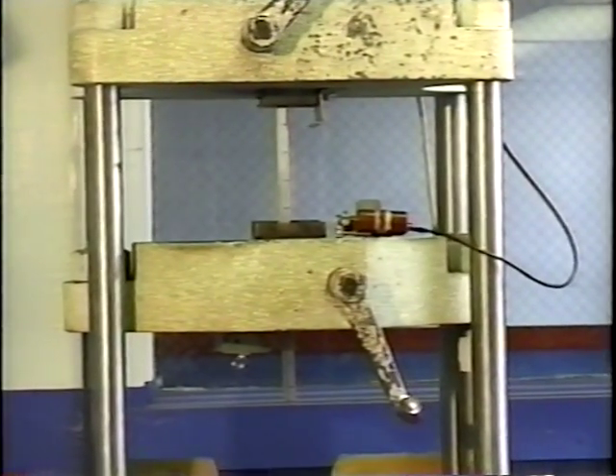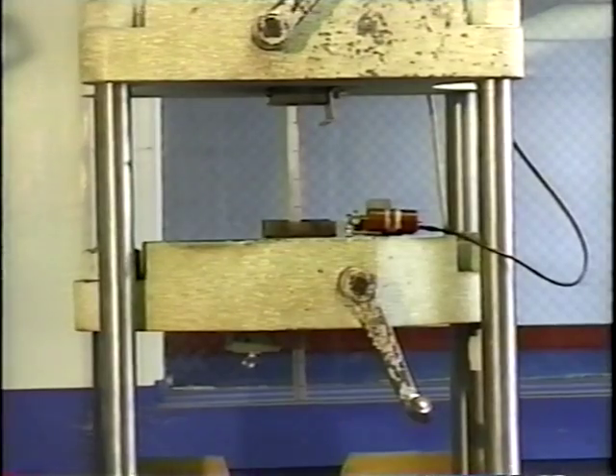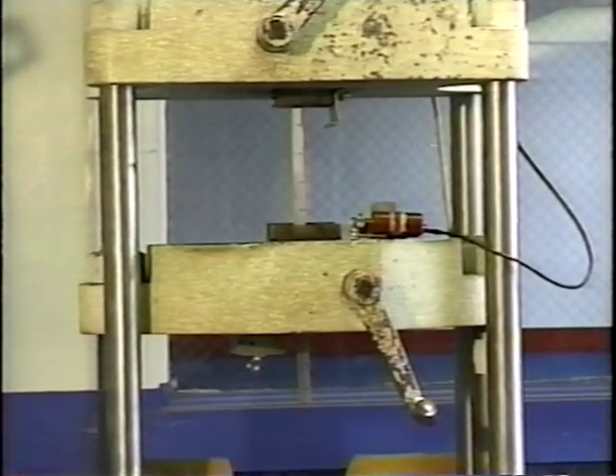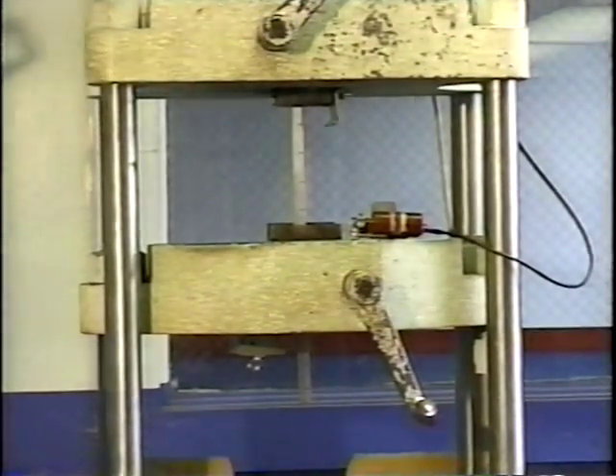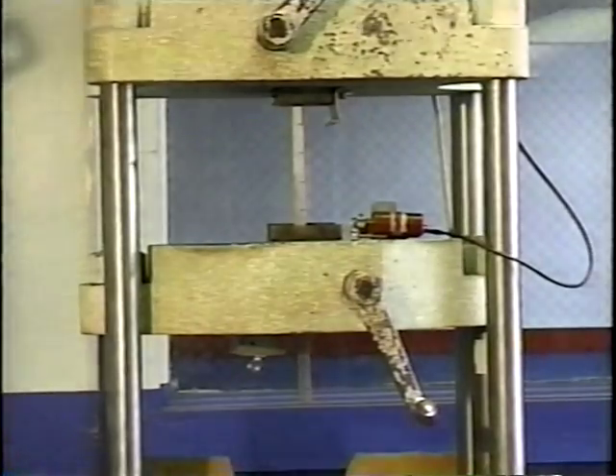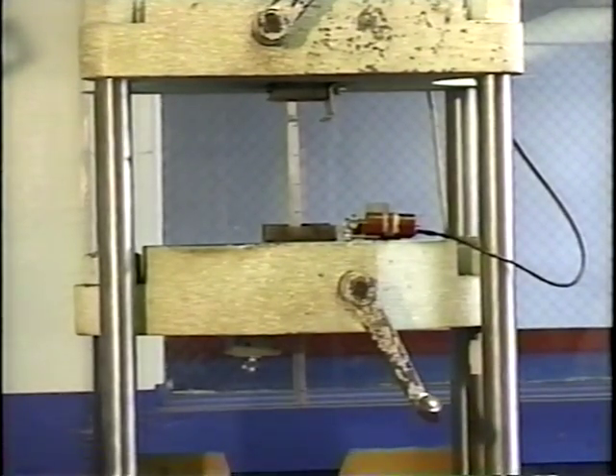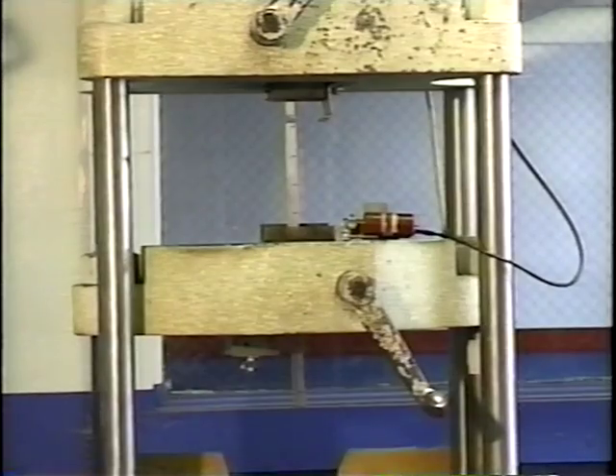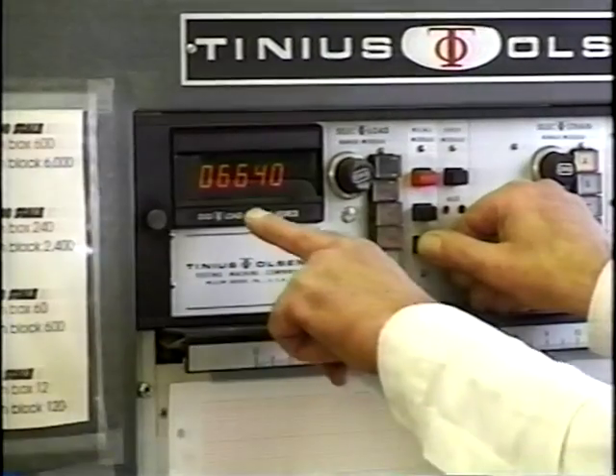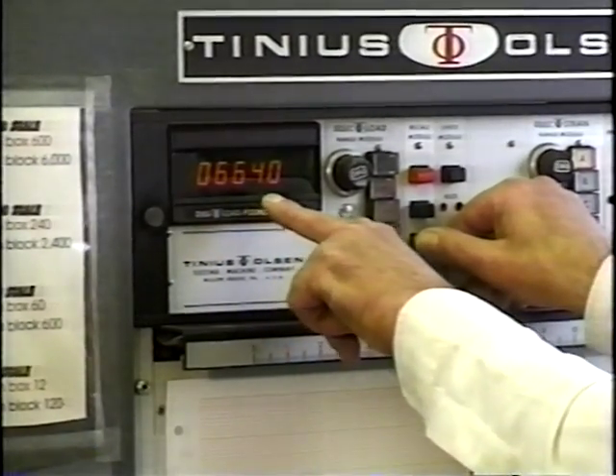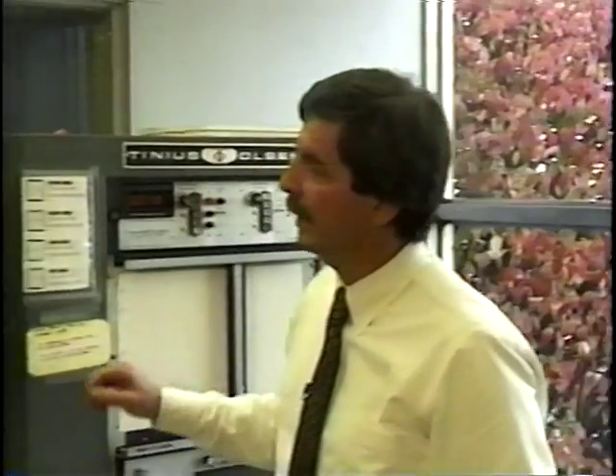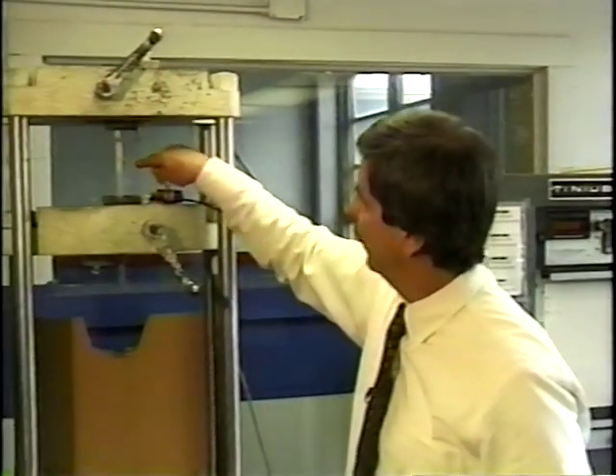We're looking at the load. It should fail pretty soon. You can see that it's not moving at all, so it's on its way to failure right now. And that's the end of the test. Then we read the load, and you can see that it broke at 6,640 pounds. And you can see that here in the sample, it broke.